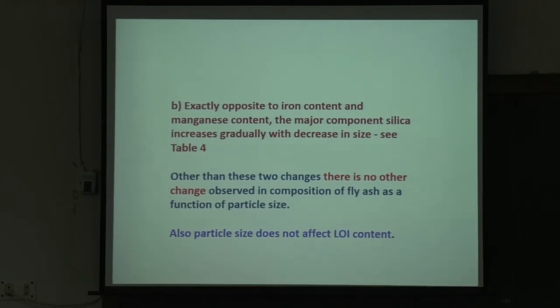Other than these two changes, there is no other change observed in the composition of fly ash as a function of particle size. Also, this is important: particle size does not affect LOI content. The particle size is not related to carbon, and LOI is the unburned carbon, so particle size does not have an effect on LOI.